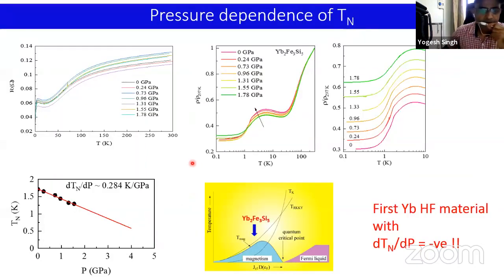So where is ytterbium placed on the Doniach diagram? Is it closer to the quantum critical point or away from it? So this can be addressed by high pressure measurements, which I show here. So without going into details, let me just say that the ordering temperature is suppressed when pressure is applied. And this is shown here, the TN versus pressure, and it goes down.